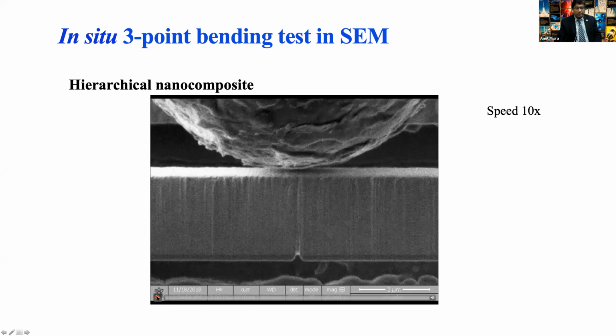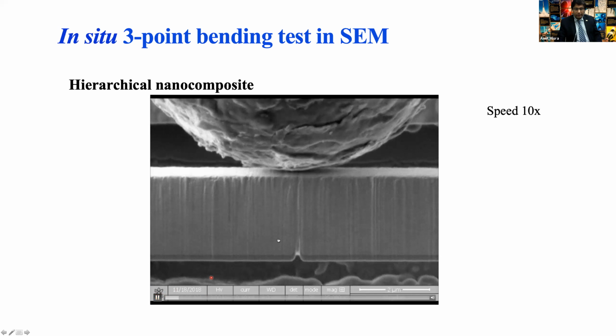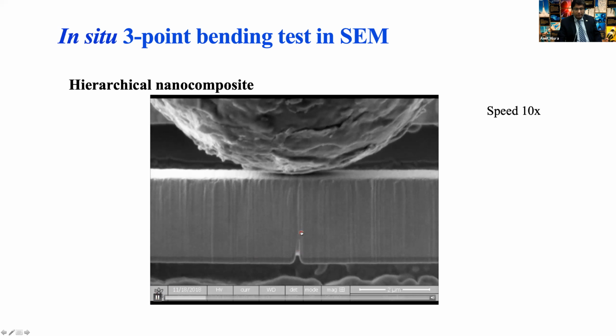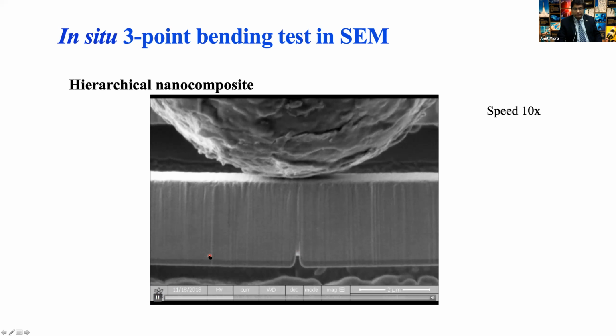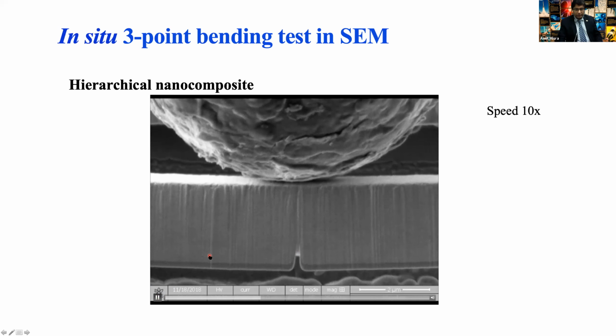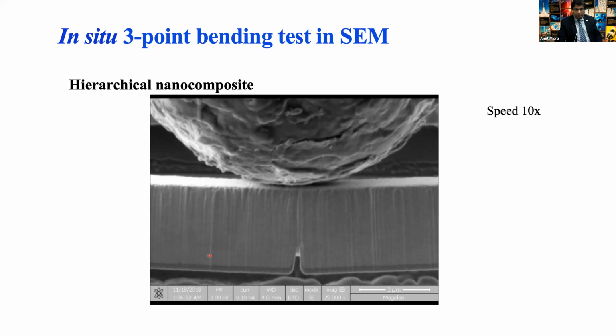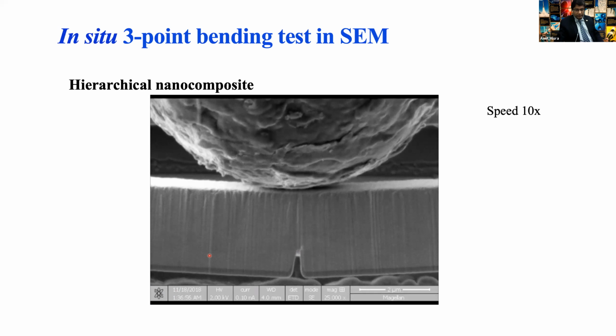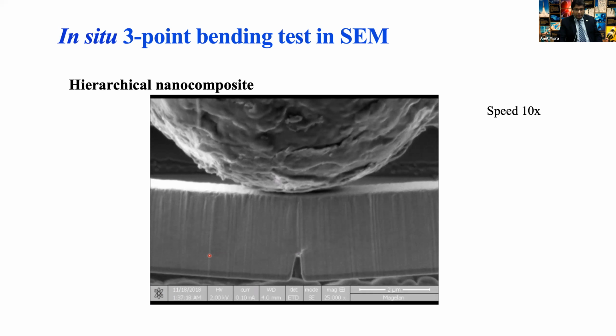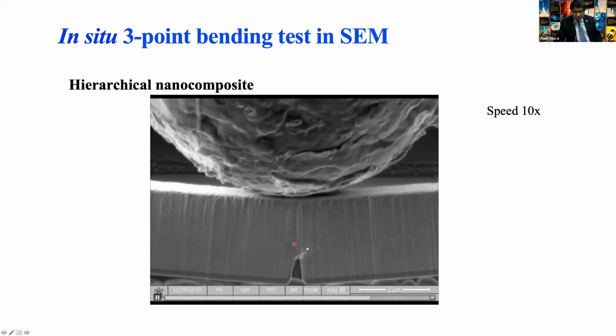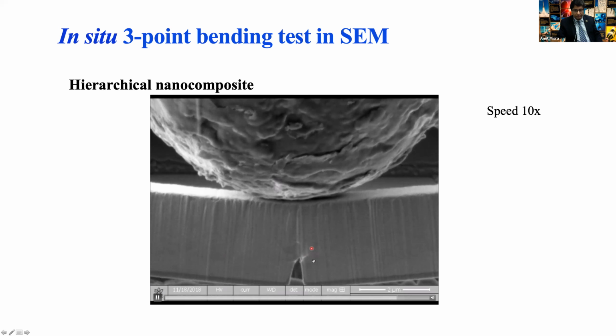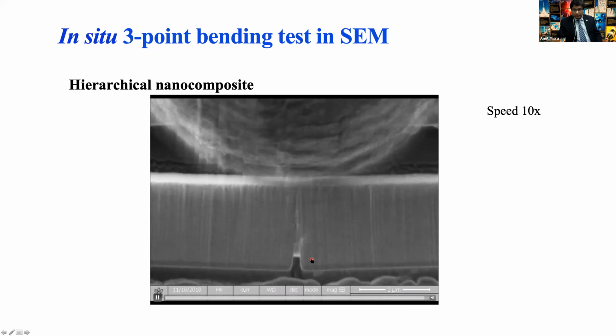Now, the way this surface is prepared, this is as FIB cut. So in this case, we don't see the contrast from the two structures. If I play that movie again, you'll see the crack will form, and you'll see the crack is not able to propagate. It will just jump from here to there. It shows the structure is tough, but it is not able to show exactly what you are asking, which is, can you track that it is going from one composite to the other? Because I don't see the contrast on this image in situ when we are doing the test.